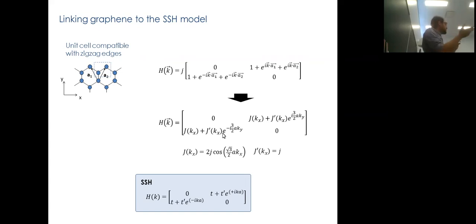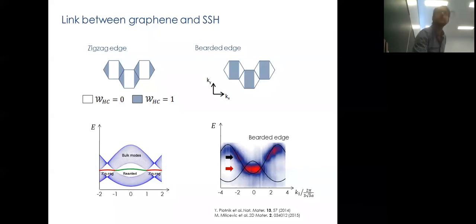And whether or not it is topologically trivial depends on the ratio between J prime and J. You see that this will change throughout the Brillouin zone because J depends on Kx as a cosine. So eventually J prime will be bigger than J, or smaller than J. And so if we do this, we can calculate a winding number for every vertical cut in the reciprocal space. Depending on where we are, we have regions where this invariant is one, in blue, and regions where it is zero, in white. Each time we change from one to the other is a place where we cross a Dirac cone. And this is normal because this is a place where we close the energy gap and reopen it.